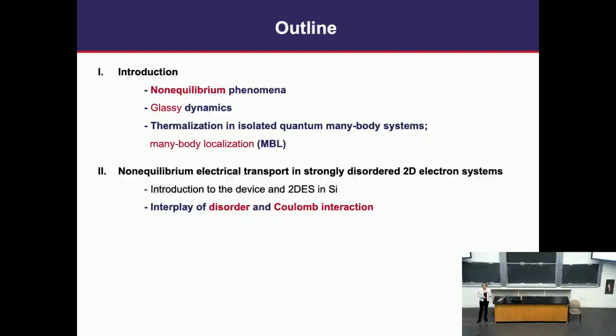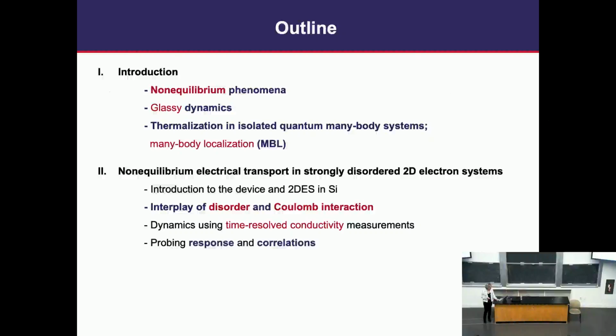To study the non-equilibrium properties, in other words the time-dependent behavior, we measured time-resolved conductivity, because this is what we do mostly, we measure electrical transport. And we use different protocols designed to probe both the response of the system to an external perturbation and the evolution of correlations with time.